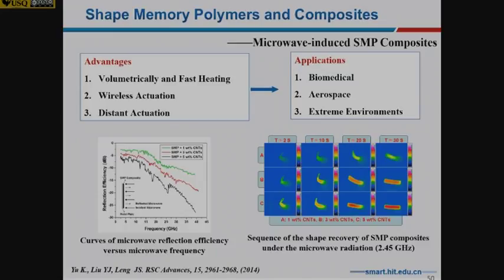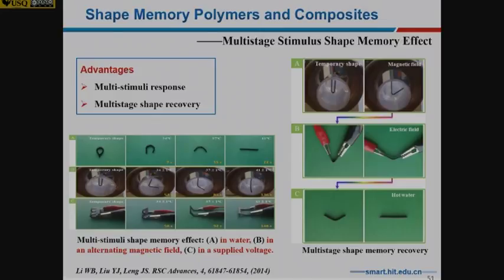With microwave, because the carbon nanotube can absorb microwave, you can have a fast actuation, and also, importantly, wireless and distant control of the shape changing. So this is a multi-stimulus responsive polymer, which means the polymer has some iron oxide and conductive particles. You can see this one can respond to a magnetic field, then change by electric field, then change by hot water, which is temperature. So it changes to different shapes.